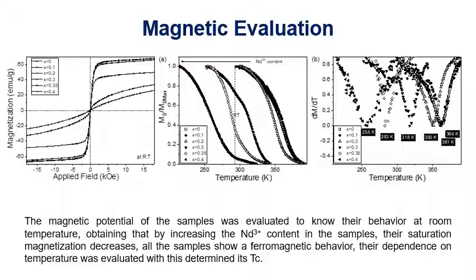The magnetic properties of the samples were evaluated to know their behavior at room temperature. As the neodymium content increases, the saturation magnetization decreases. All the samples show ferromagnetic behavior. Their dependence on temperature was evaluated with magnetization versus temperature curves.